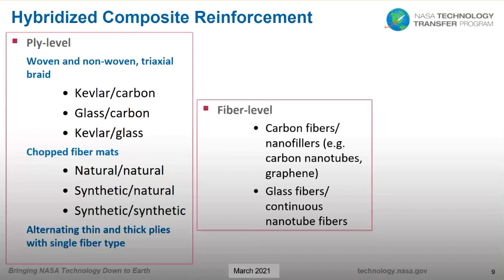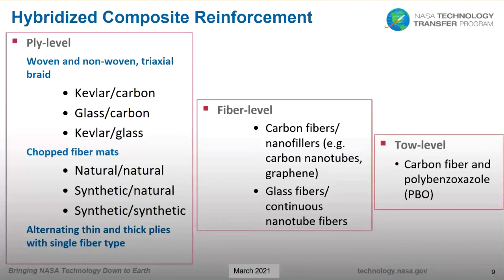Then there are fiber level hybrids, where nanoparticles are grown from the surfaces of carbon fiber. That's a more popular example. And I've also seen in literature glass fibers that were wrapped with continuous carbon nanotube yarns around those micron size individual glass fiber filaments. And then there are hybrids that may exist at the tow level. A common example of this is a commercially available spread tow consisting of carbon fiber with polybenzoxazole.